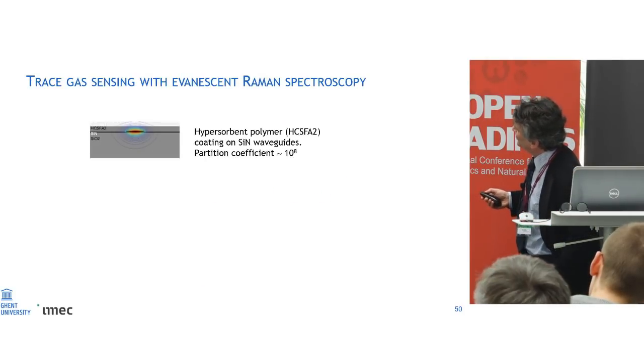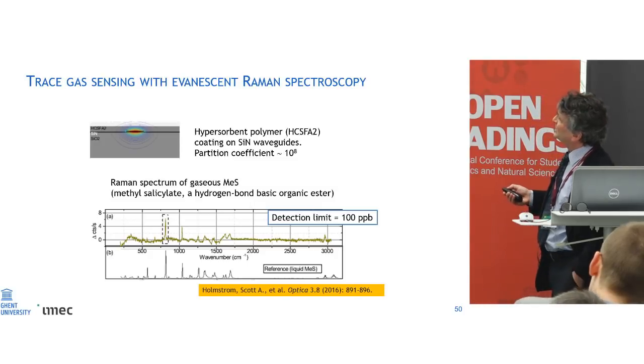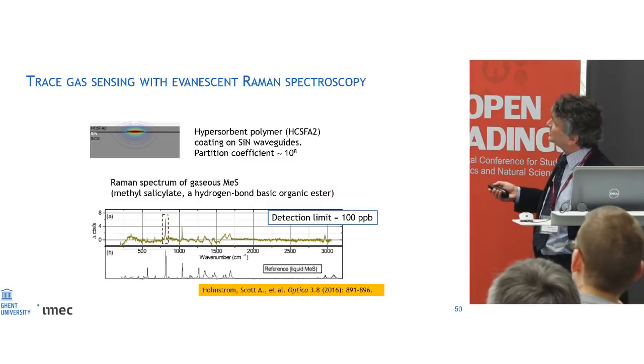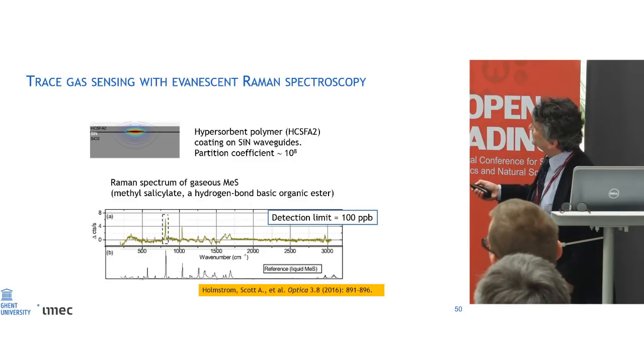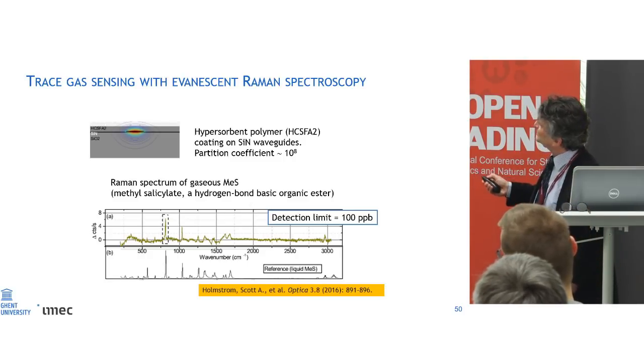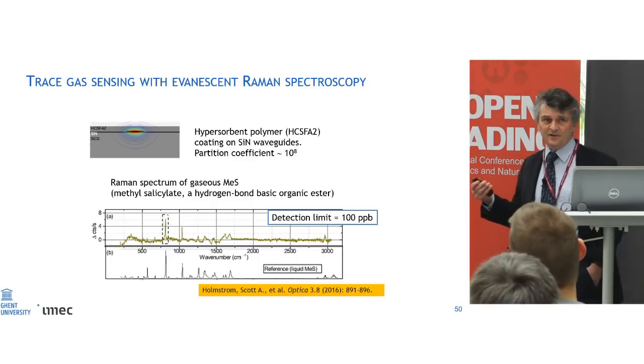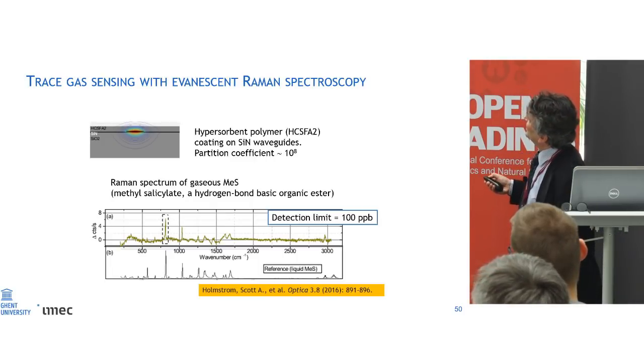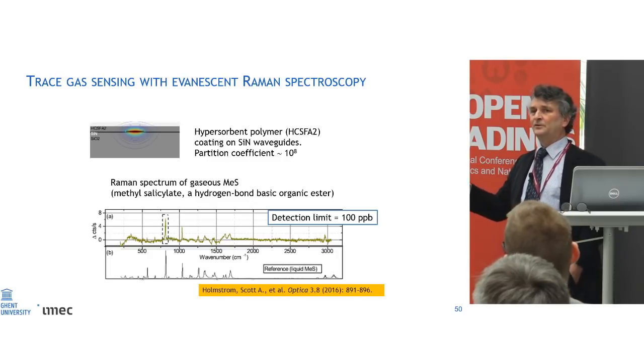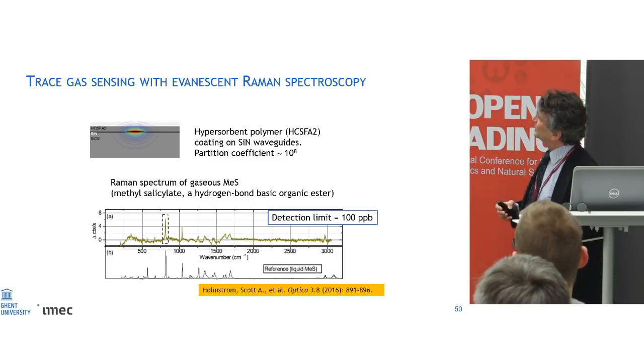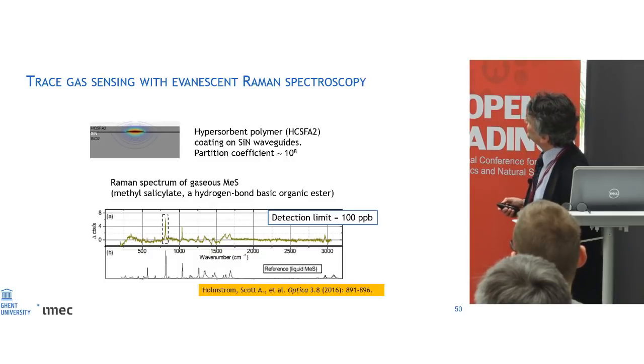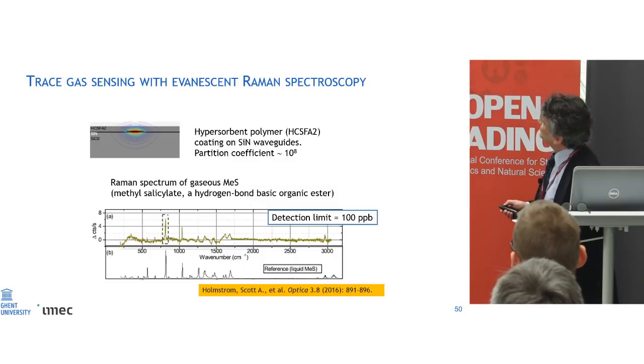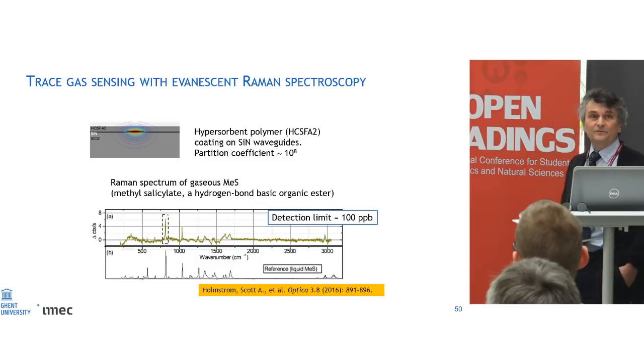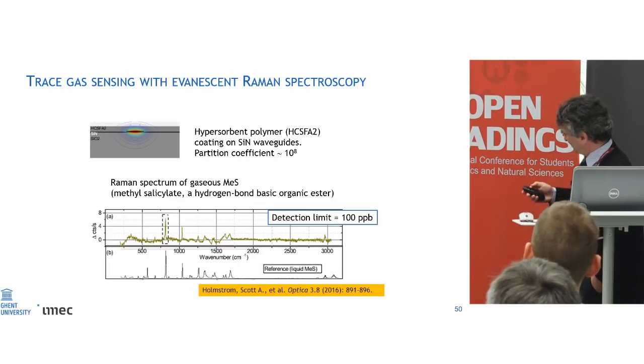This is not work from ourselves, but from a US group. The same method has also been used for trace gas detection, where actually on top of the waveguide, they put a hypersorbent polymer, which adsorbs gas molecules with a very high partition coefficient, so ratio of density in the gas phase versus ratio of gas molecules in that hypersorbent polymer. And with that, they could get spectra from a gas, in this case it was methyl salicylate, down to a detection limit of 100 ppb. That's quite an impressive result, I believe.